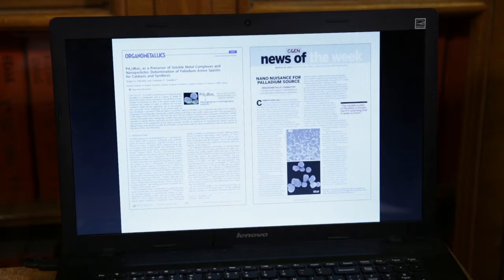This was published in 2012. And we have discovered that in regular solutions of a very well-known palladium complex, which is Pd2(dba)3, which is usually used for doing solution-state organometallic chemistry with palladium and also homogeneous catalysis, this complex can readily decompose and form nanoparticles of palladium. Of course, this phenomenon was known, and it was known that palladium complex, especially Pd2(dba)3, can decompose to give nanoparticles. But what was surprising is that this decomposition is really very easy, very rapid and very fast.